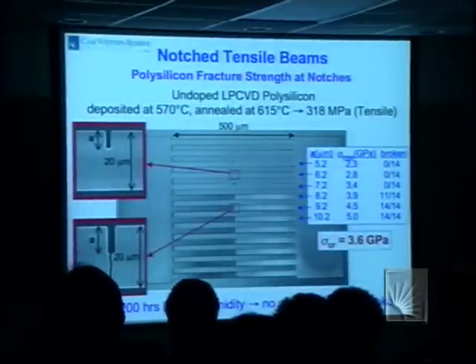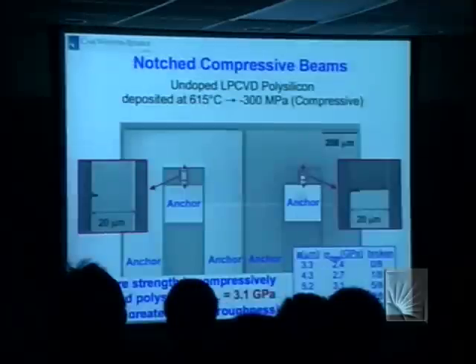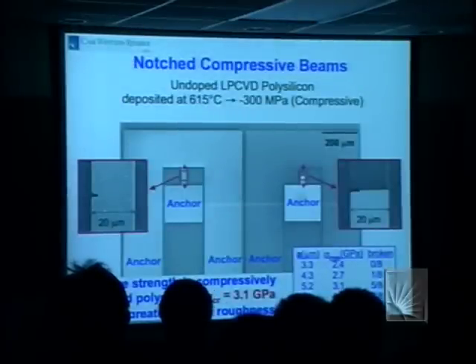I didn't show you the roughness, but the 570 material is much smoother because it's this amorphous material that crystallizes. It's much smoother than when you get to this compressive material, and the difference between 3.1 and 3.6 GPa is just the difference in surface roughness between these two deposition temperatures.